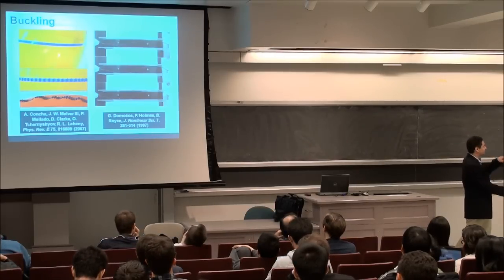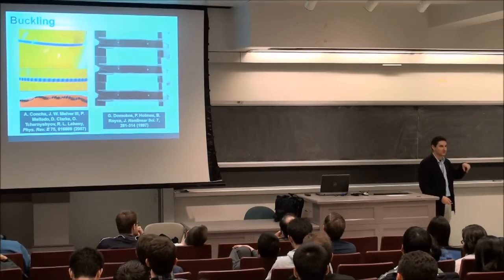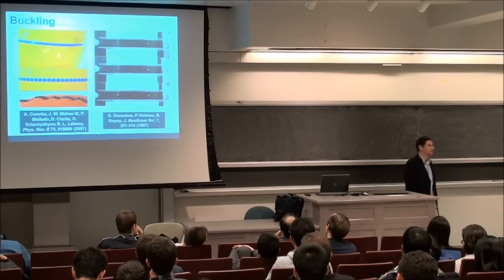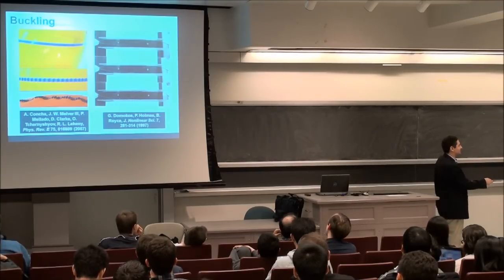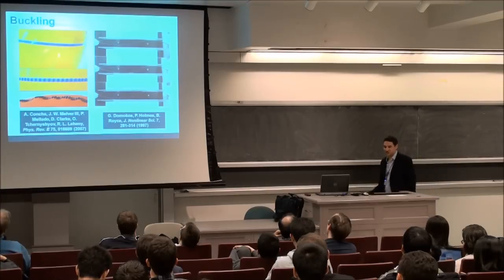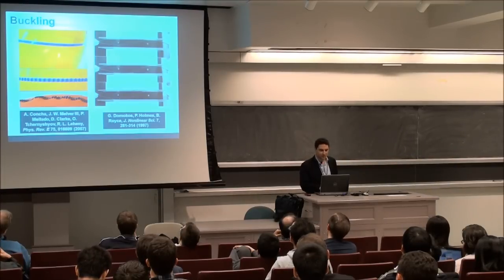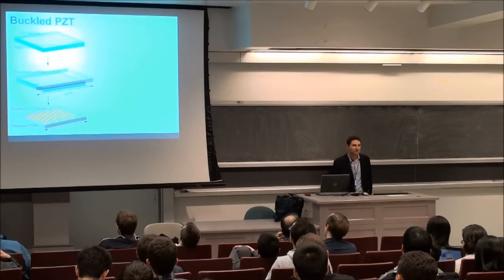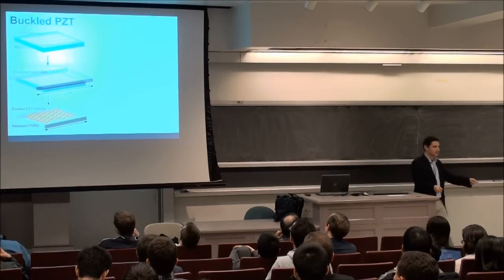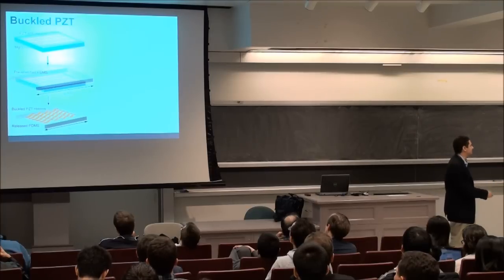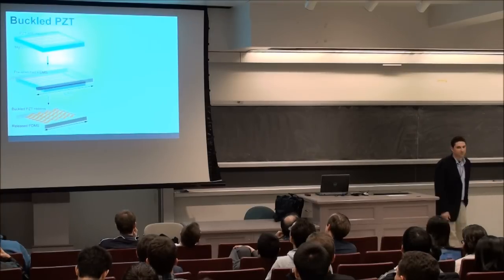And you can actually, by using your finger, switch between different buckling modes, different Euler buckling modes here, between these two constraints here, okay? So it's an interesting problem, this constrained Euler buckling. Of course, in our case, we did the John Rogers trick, where we basically stretch our PDMS down and then print it onto the PZT here and then release. So you can get these buckles here.